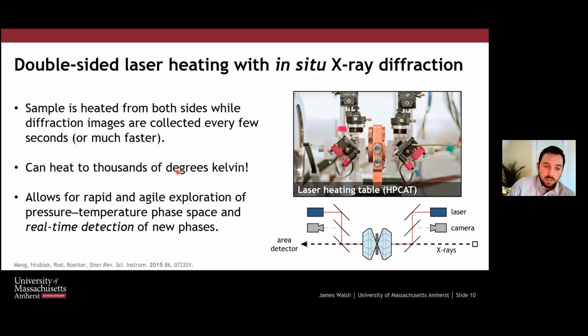I typically don't go that high unless I do something wrong and I'm not paying attention and it couples and runs away. Usually we're around 1,000 to 1,500 Kelvin, but you could go to much, much higher temperatures with the laser heating. And what this allows us to do then is have really, really fast feedback from the reactions as we perform them. We can be collecting diffraction, and we typically use the seconds scale, 5 to 10 seconds. We're collecting a new image and looking at it in real time. And I'll show an example of that.